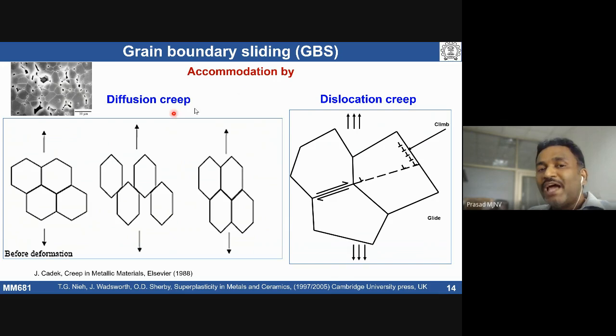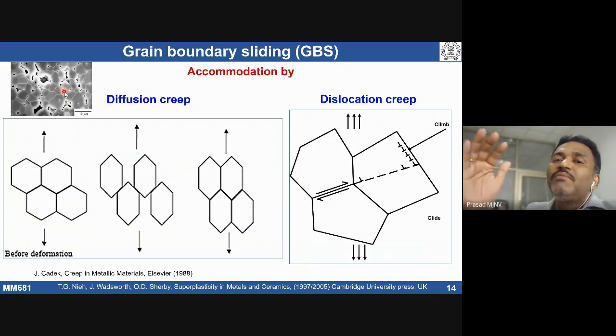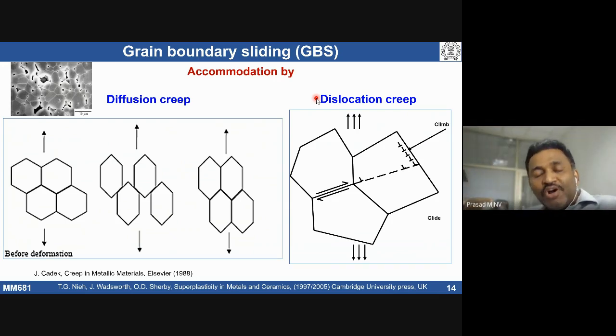If one of them happens, then your tendency for cavitation is going to be minimal. If either of them is not happening, then what happens? It is going to lead to failure. So that's what we are talking about. If you deform material at 0.3 times the melting point, with the same grain size, assume they have 1 micrometer grain size, one I deformed at 0.3 times the melting temperature, one I deformed at 0.7 times the melting point.